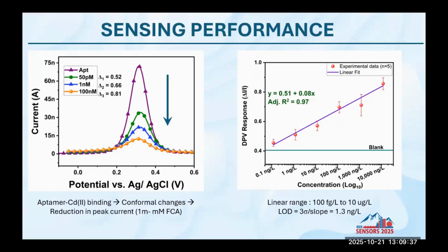Using this, we performed this set of experiments with replicates, and we observed the calibration curve to have a very linear form. We obtained the LOD to be 1.3 nanogram per liter, while the safe limit for cadmium is around 5 to 10 microgram per liter. We have obtained the LOD to be quite lower than the safe limit.